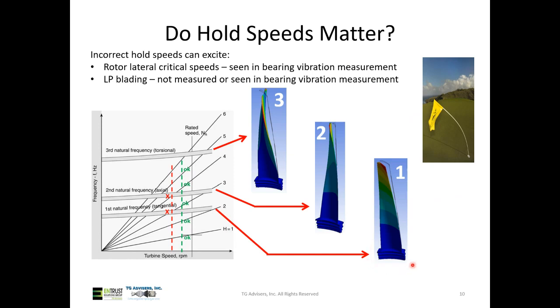Okay. Well, the same is true when we back off speed. So what we have on the left side is a Campbell diagram. It's showing the natural frequencies of the blade, first mode, second mode, third mode. And what you're looking at is here's running speed. And we just want to make sure that these natural frequencies don't hit at 1 times, 2 times, 3 times running speed, 4 times, 5 times, 6 times. So we can tell here it's a well-tuned blade. The lines of the actual frequencies are sitting between multiples of running speed.